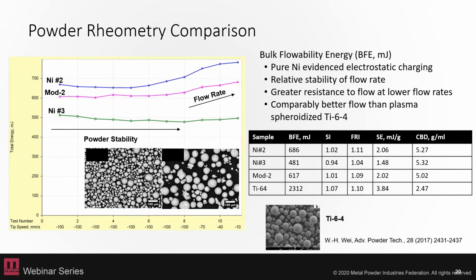And this measurement gives you an indication of the stability of your powder as it undergoes continuing flow measurements. And that's the first 7 measurements within this scale. And then at different flow rates, it can increase the energy required to make that powder flow. So in this case, the pure nickel powder evidenced electrostatic charging. All these powders had fairly uniform stability of the flow rate, but then again, as the speed of the propeller was increased, that actually showed a greater resistance to flow at lower flow rates.